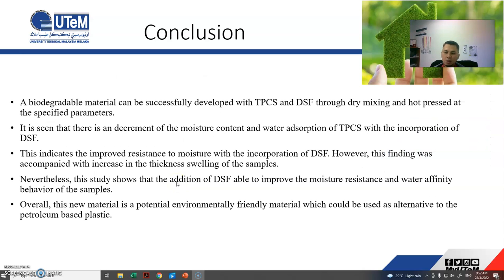As a conclusion, biodegradable materials can be successfully developed by using TPCS and durian husk fiber, or durian skin fiber. There is a decrement in the moisture content and water absorption with the addition of the durian skin fiber, and this indicates improved resistance to moisture with the addition of DSF. However, this finding was accompanied by an increase in the swelling of the sample. Nevertheless, this study shows that the addition of DSF is able to improve the moisture resistance and water affinity behavior of the samples. This is the most important thing in the study. Overall, this new material is a potentially environmentally friendly material which could be used as an alternative to petroleum-based plastics.